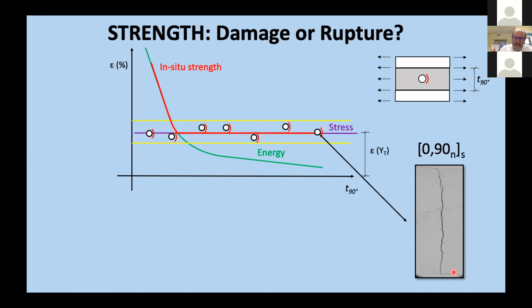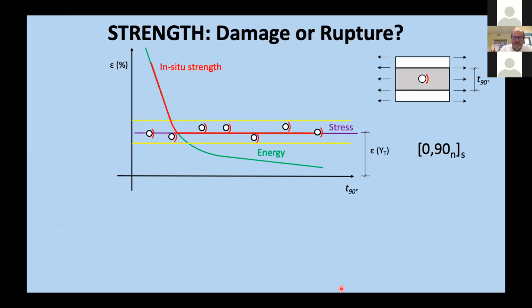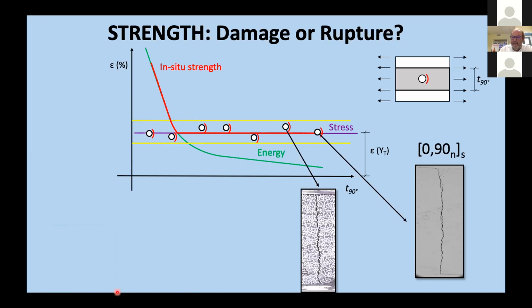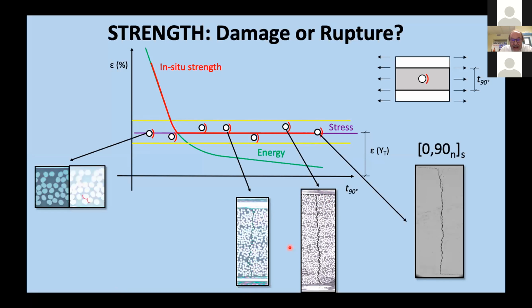If now we go to a smaller value of the thickness, we have something similar, but for instance, in this case, without delamination. Even with a smaller thickness, we have something like this, where we have not reached totally the thickness of the 90 degrees, but continue in a similar situation as previously. If now we move to this case, then we have clear indication of isolated debondings.